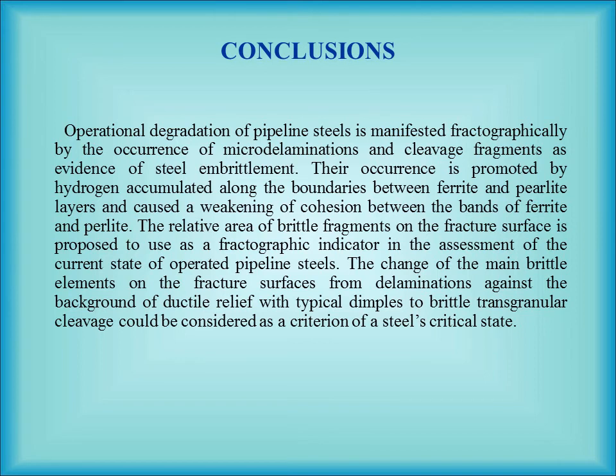And finally, conclusions. Operational degradation of pipeline steels is manifested fractographically by the occurrence of microdelamination and cleavage fragments as evidence of steel embrittlement. Their occurrence is promoted by hydrogen accumulated along the boundaries between ferrite and perlite layers and causes a weakening of cohesion between the bands of ferrite and perlite. The relative area of brittle fragments on the fracture surface is proposed to use as a fractographic indicator in the assessment of the current state of operated pipeline steels.